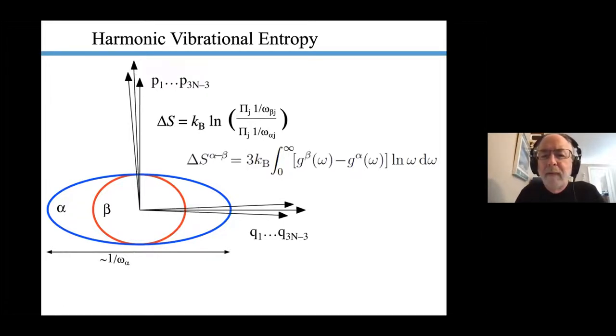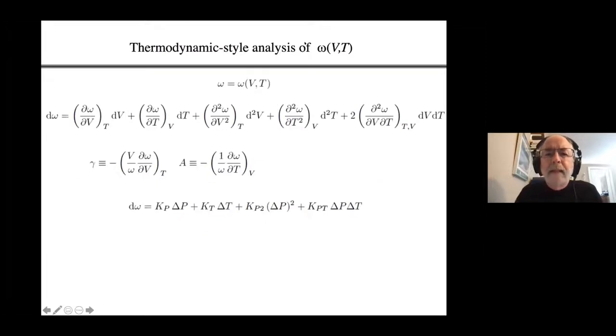It works pretty well above the Debye temperature. At low temperatures in a material, you have to worry about occupancy factors, so the densities of states aren't quite weighted the same way, but that's correctable. The key thing is we need to know what these frequencies are. And to get the vibrational entropy at temperature and pressure, we want to know how omega changes with temperature and pressure. And let's just look at that for a minute here, in a simple way, with the two variables, volume and temperature. Now, I like volume because that sets the size of the crystal and that sets the distance between the atoms.